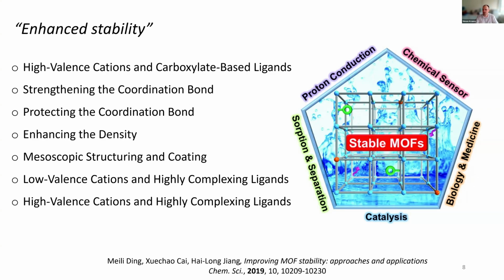by the aspect of stability. In fact, MOF-5, based on the zinc oxide clusters, is relatively hydrolytically unstable. So when it is exposed to especially water vapor, it will decompose into more stable zinc oxide. Now, of course, for certain applications such as gas capture, an enhanced stability is a critical aspect.